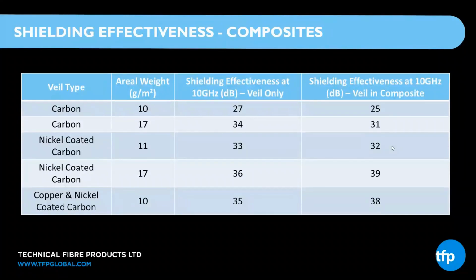This slide points to how the veils used in composites are similar to how the veil is measured on its own. In the middle column, the veil only was tested at 10 gigahertz. You can see that the carbon at 10 GSM yielded about 27 dB, and within a composite, which was a glass epoxy prepreg, it was 25 dB. So really no significant change here. I will also point out how the carbon is a little less effective than the nickel coated carbon, and that's less effective than the copper and nickel coated carbon.